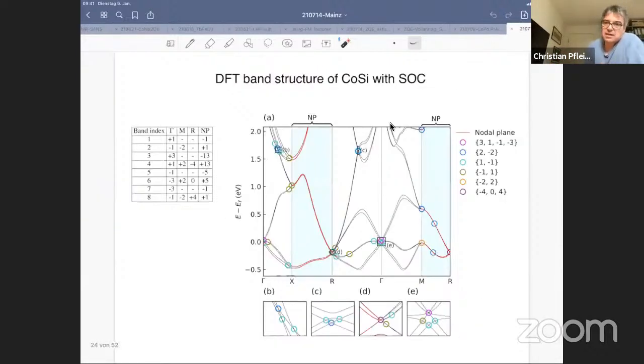Okay, and so what Andreas Schnieder and Kirill Alpin in particular, and Moritz Hirschmann, did was a full analysis with different methods of the band structure, and they calculated all of the crossings, right? So this is the band structure of cobalt silicon. Here I'm showing the picture where we take spin-orbit coupling into account, which is quite weak. It's about 10 to 50 milli-electron volts at these locations.